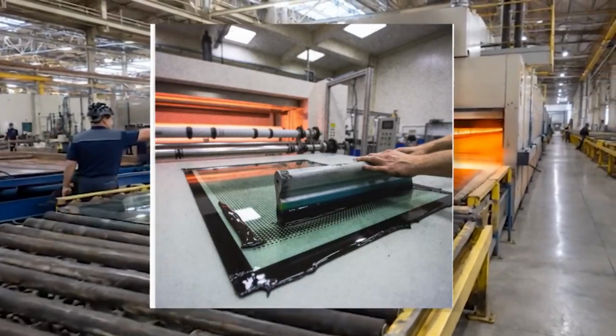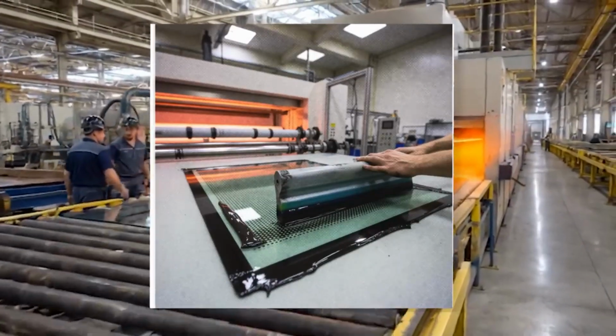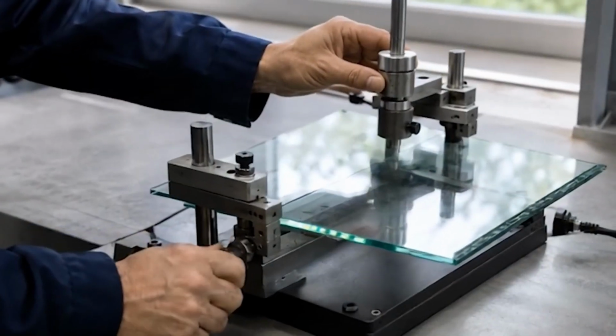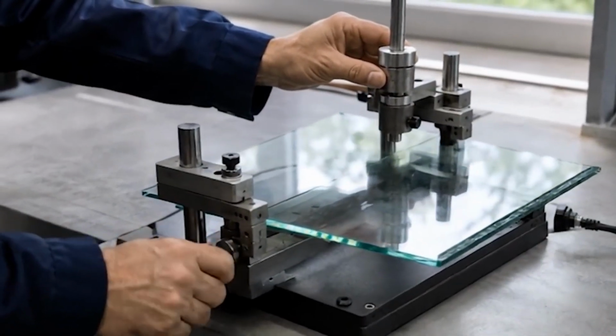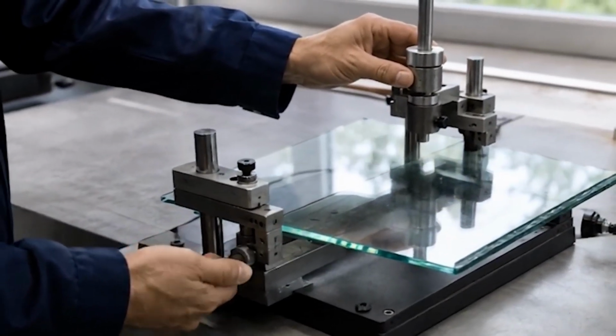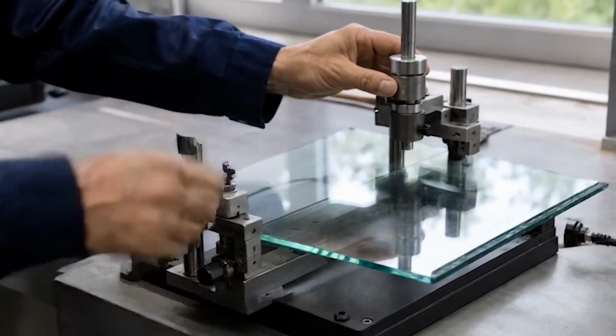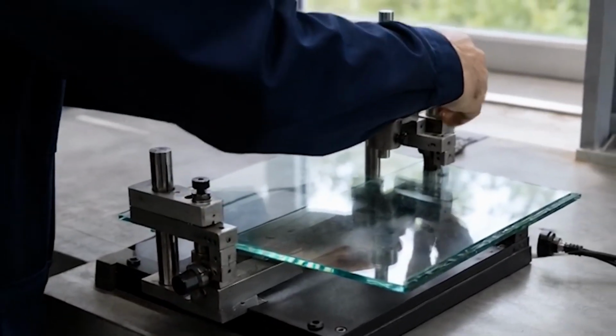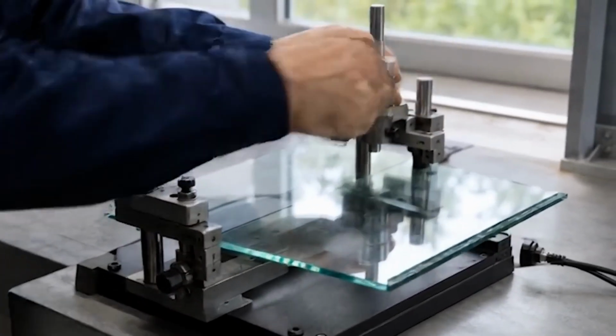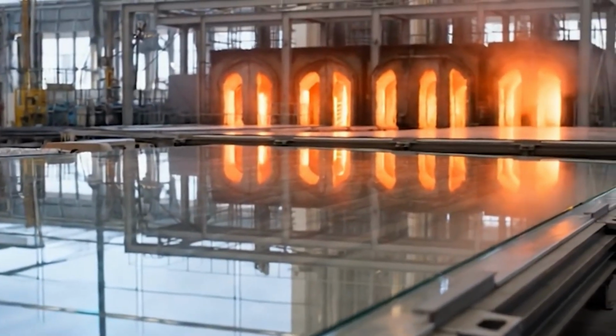However, engineers soon noticed something alarming. The glass was cracking during production. The fractures always appeared near the edge of the black border. Nobody could understand why. The answer came from physics. Before automotive glass can be installed, it must be tempered. The glass is heated until it becomes soft and then rapidly cooled. This process creates internal stresses that make the glass much stronger and safer.